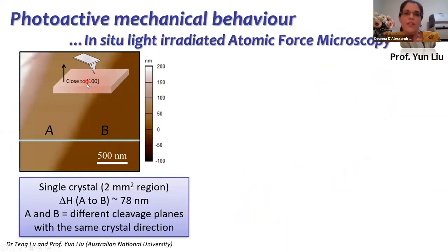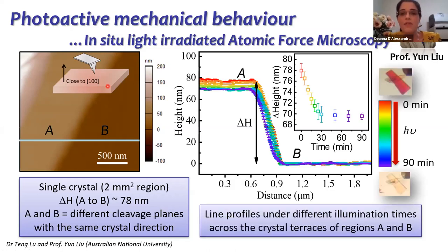What is interesting here is the connection between this double 2+2 photocyclization and the mechanical properties. So here we have an AFM experiment. This is an in situ experiment under light irradiation. This is a single crystal, and quite conveniently we have a couple of crystal planes, A and B, and we're just tracking the tip of the AFM across those crystal planes. So what you see, if you look at the height difference between A and B as a function of irradiation time, is that there is a change in the height of the cleavage plane of around about 11%. So there's a mechanical property, if you like, attached to that photocyclization event.